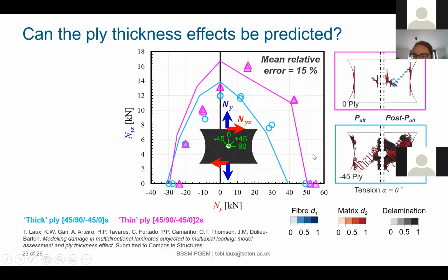So in laminate 1 tension, it's predominantly delamination, which is the black area here. So the plies separate. Whereas in laminate 2, actually, you have fiber failure, tension failure of the fibers, which is the blue one. So very different patterns.